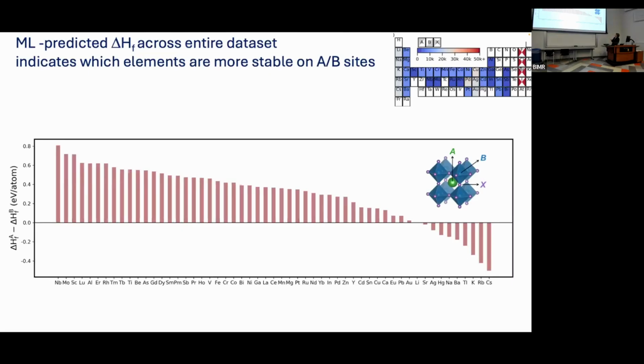And eventually there's some transition. Some elements have very little preference. And then there's a transition where the majority of elements strongly prefer being on the B site. So there's only a subset of elements that can energetically form stable perovskites on the A site, if used on the A site. So this dramatically narrows down this large chemical space of how we can select elements for different sites in order to find new stable materials.